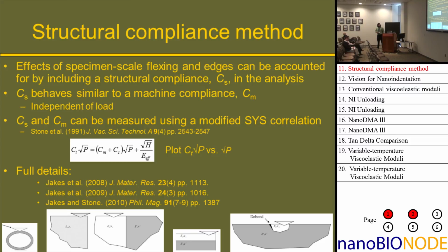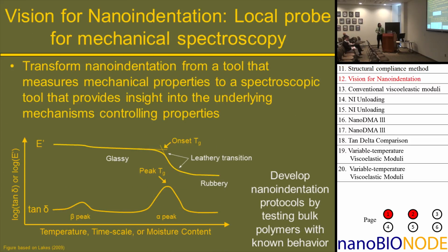In the case of a thin film like this, the assumption that hardness and modulus are independent of depth wouldn't be valid, but you can still use a variation of this to account for a free edge and a layered specimen as well. All the full details are in these papers, and I'd be happy to talk to you afterwards as well. The other issue with wood polymers is that they're polymers, and so the materials are really going to be time dependent.